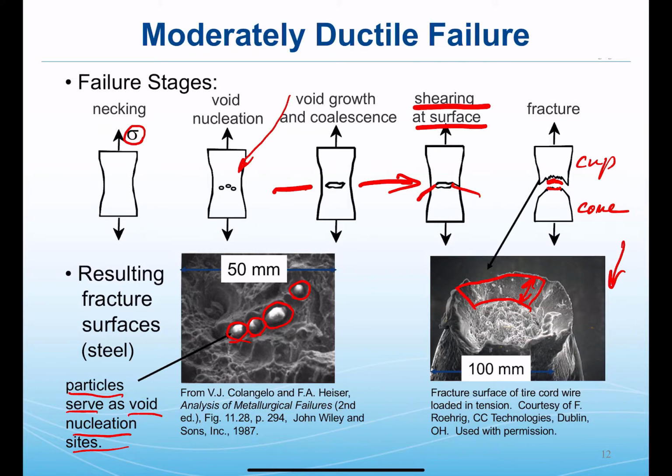Okay, so clearly the internal crack where lots of voids had coalesced occupied an area about that much, and then ultimately shear occurred to create the sort of final cup in the cross-section of the material. Okay, so these data, for example, here were for a steel material that went through ductile failure.